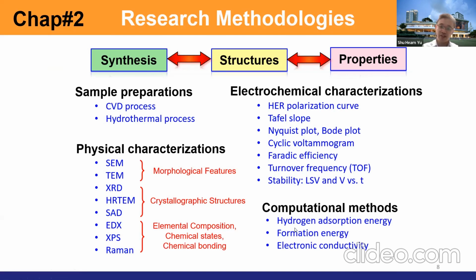Then after that, we will characterize the sample using physical characterization methods, for example SEM and TEM to see the morphology features, XRD and HRTEM to see the crystal structures, and XPS to see the elemental composition, chemical state, and chemical bonding. After this physical characterization, we will do electrochemical characterization. I think you guys are very familiar with the HER polarization curve, Tafel slope, Nyquist plot, Bode plot, cyclic voltammetry, Faradaic efficiency, and turnover frequency to find out the intrinsic activity of the HER catalyst. And also we will test the stability of the material by running repetitive LSV or holding the current, and then we see whether the potential will change over time.